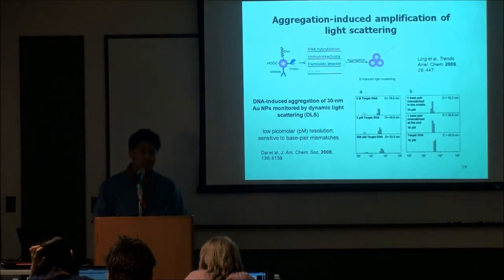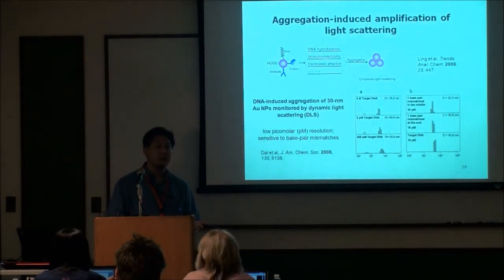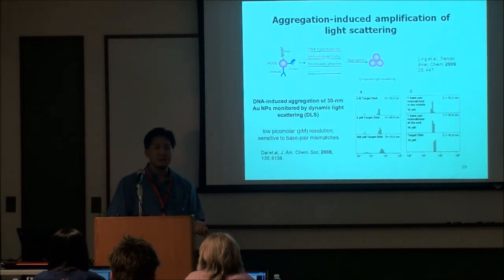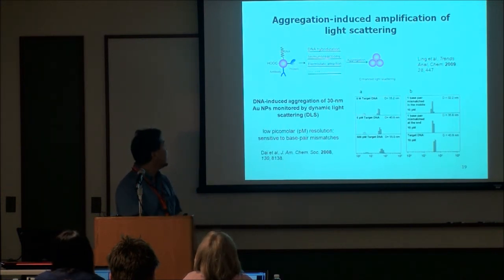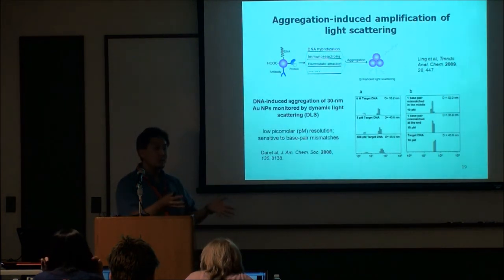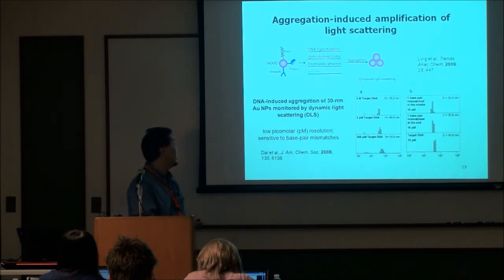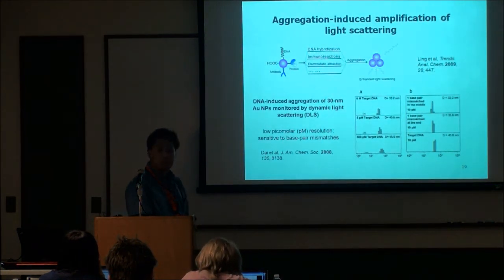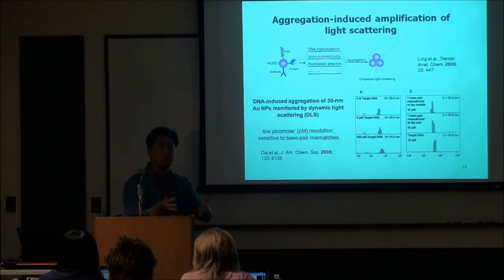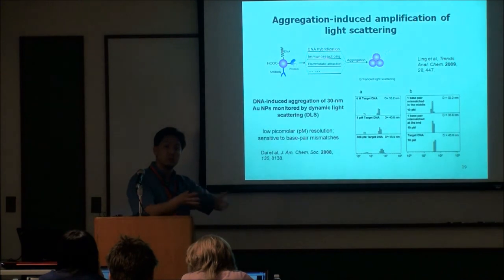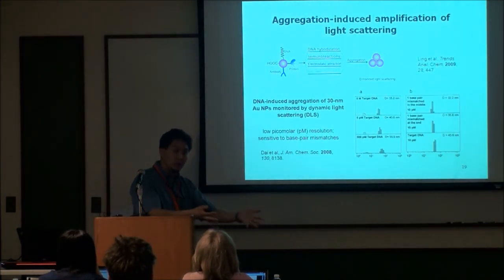Okay, now there is, of course, more than just simply the wavelength of the nanoparticle that you can take advantage of. One that's sort of underappreciated is that the nanoparticle scattering increases with size. Okay? And so if you take a small particle and you cause it to aggregate because of some protein-protein interaction, the size of the particle increases effectively, and that will cause the scattering to be much brighter. It's much more efficient and has a higher extinction coefficient of interaction with light. Okay? And so being able to detect something based on amplitude changes can be useful for lots of applications. And of course, there's a combination of these two. As you aggregate the particles, this will also effectively cause the size change to cause the plasmon resonance to shift. So you can get both a frequency shift as well as an increase in the scattering amplitude.